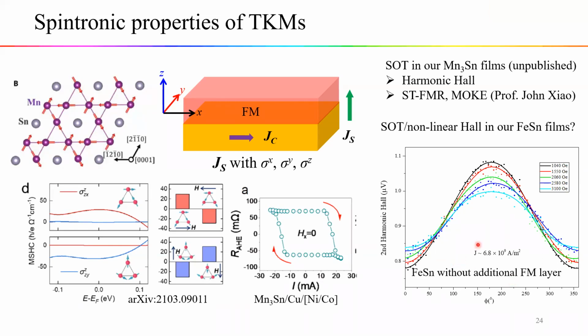Okay. So basically the Iron-tin itself gives you a signal almost like a bilayer. Although that also has a layer like platinum ruthenium, we don't know what it is. It could be due to magnon scattering, probably a likely scenario. But that's a fairly large signal, because in other bilayers, even with the ferromagnetic layer, in some cases we couldn't even get this signal. Okay, thank you. Sure.